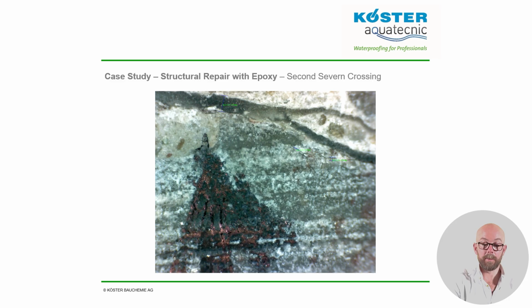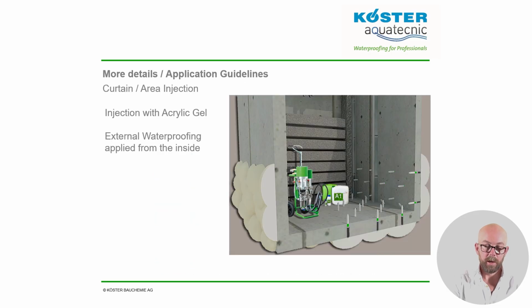Analysis of the core samples under electron microscope revealed that all cracks that could be found in the specimen were fully filled with resin. The smallest crack that they could find was 17 microns. That's 17 thousandths of a millimetre. This could be achieved with a very thin epoxy and by vacuum injection. The main contractor in the project has now changed, but the work is continuing using the same resin and procedure.